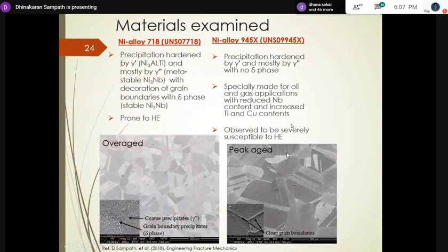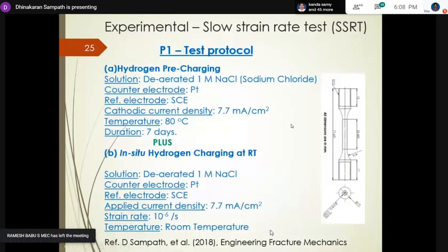Peak aged is one particular size of the precipitate at which the material attains its highest strength. So this is a peak-aged microstructure. You can see there are big grains and no grain boundary precipitates, which they made for oil and gas. And the experiment I'm showing here: we used this cylindrical specimen, based on a NACE standard. That's the standard for conducting slow strain rate tests.